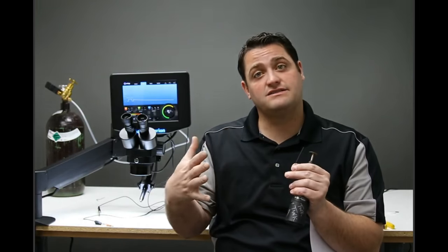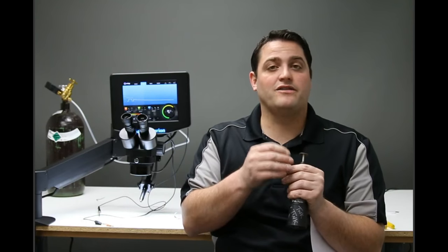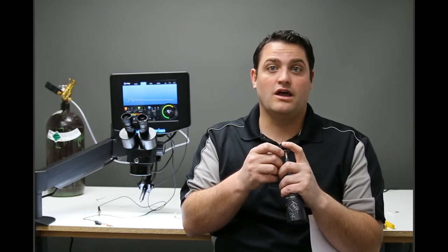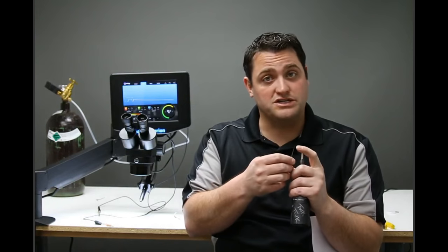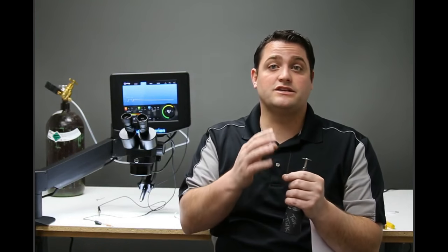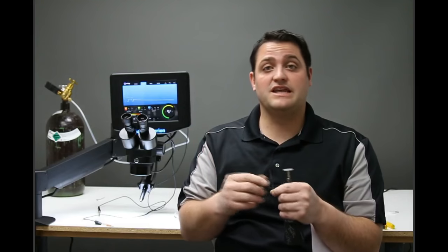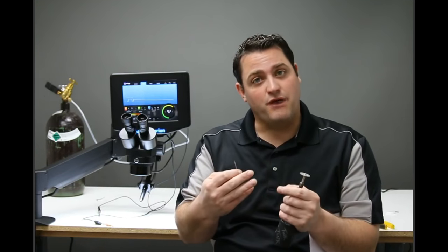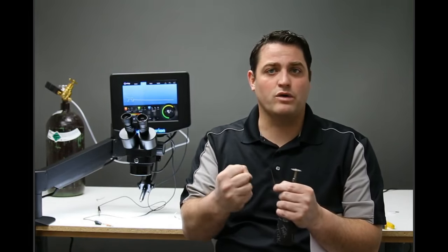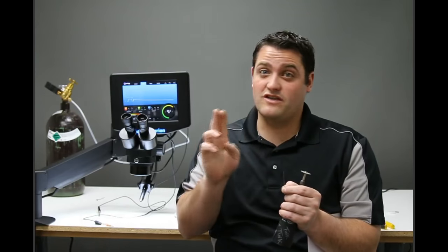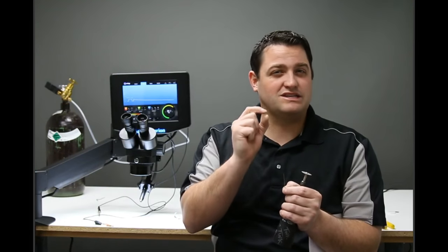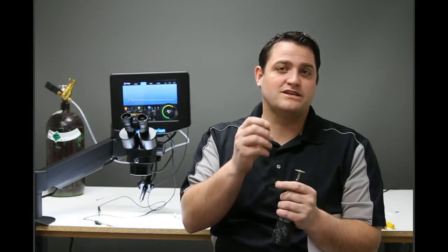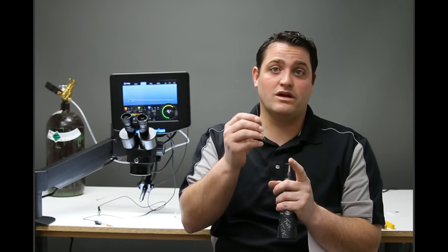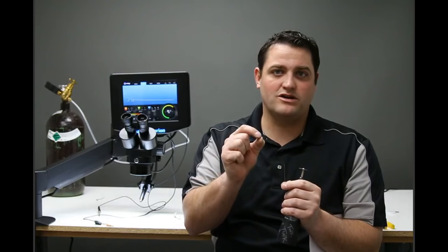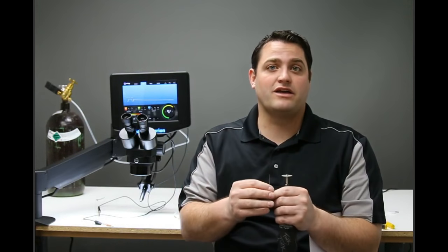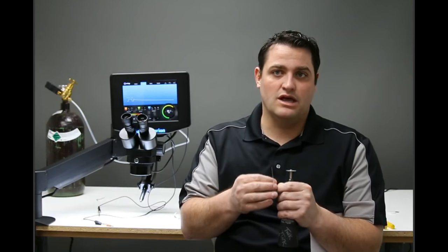So depending on the thickness of the silver is in relation to how much we truncate that electrode. We talked a little bit about that, and we had some questions about how much to truncate it. It's a direct correlation to the amount of energy or melt spot that we're putting in, how much melt we want. If we want a lot of melt, we turn that up and truncate it a lot. If we want just a little bit of melt, then we want it just a little truncated or even sharp, at very low energies, and that'll give us a more desired result.